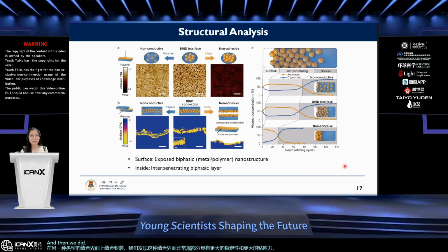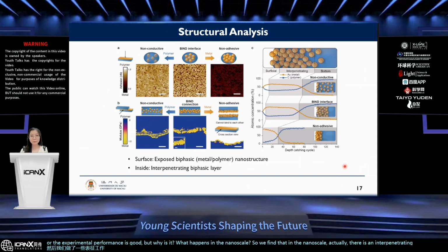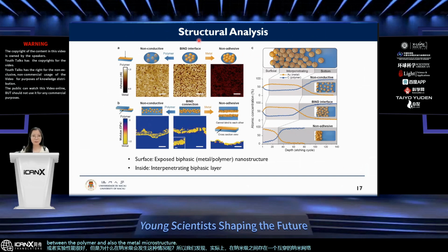Then we did some characterization work to find the experimental performance is good, but why is it? What happens in the nanoscale? We find that in the nanoscale, there is an interpenetrating nano network in between the polymer and the metal microstructure. Here in the middle is the bind interface, which achieves a balance between the metal and polymer. If we increase the polymer ratio, then we will get a very adhesive but non-conductive interface. And if we increase the metal volume, we will find that the interface is very conductive, but it is not adhesive at all. So actually, our bind connection is a balance in between.